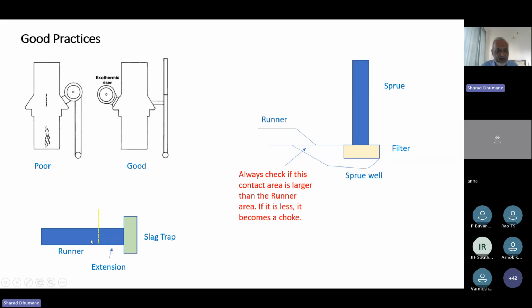So if we design our runner in such a way that the initial metal is trapped by giving an extension and then adding a slag trap at the end, then this becomes a completely foolproof, fail-proof system, so that when your metal flows into the casting, you have already trapped your liquid slag and the eroded sand, and then there is a good possibility that your castings show freedom from these defects of poor metal quality.